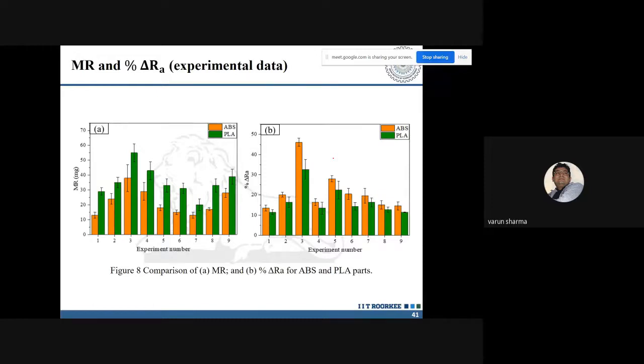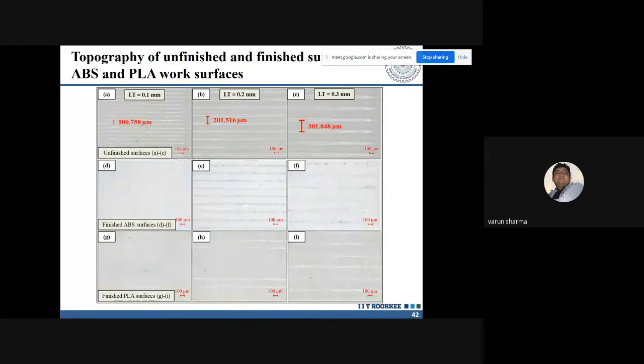For all these sets of experimentation, you see that your material removal was higher in the case of the PLA. Fine. For some parameters it is less, for some it is more. It was best for the condition of the 3. Now just look at the cross-sectional view of the surface finish over here. What you see over here is for the layer thickness 0.1 mm, the consecutive layer thickness is 100 microns. Over here it is 200 microns, that was for 0.2 mm, and over here it was 300 microns for the 0.3 mm layer thickness.